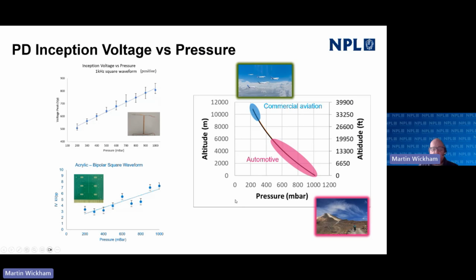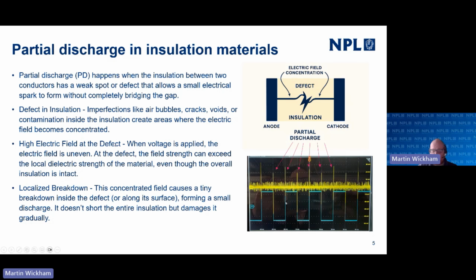Our problem occurs when, well, I'll deal with that in a minute. The problem occurs when you get repeated partial discharges. This graph shows how the inception voltage for that partial discharge is occurring. So the inception voltage is, as you increase the voltage across your electrodes, at some point you will see PD on the system. So at some point you will start to see these spikes occurring, usually at the high dV/dt,